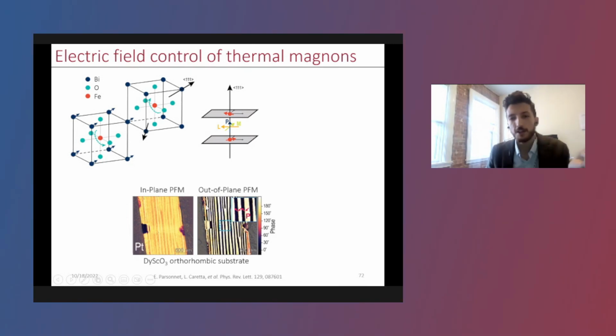What I will tell you is that there are students working on what's called single-phase, single-domain BFO, where you don't have any domain walls, and they do indeed see a first harmonic. So you can get the electronic effect if you're able to engineer these eight degenerate polarizations of bismuth ferrite correctly. Okay, thank you.